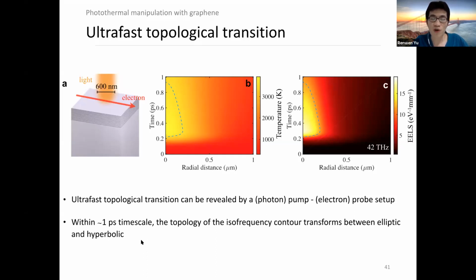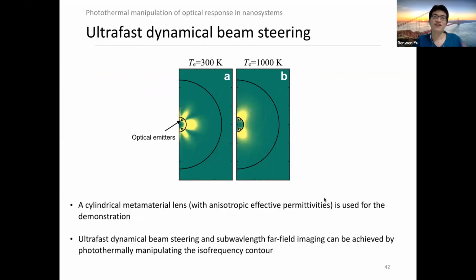So more importantly, as you can see here, within a 1 picosecond time scale, the topology of the isofrequency contour transforms first from elliptic to hyperbolic. Then we have very large EELS value. Then it goes back to elliptic. So basically, we have a really ultra-fast topological transition in this case. And another application of this ultra-fast topological transition is that we can engineer the beam steering in the far field.